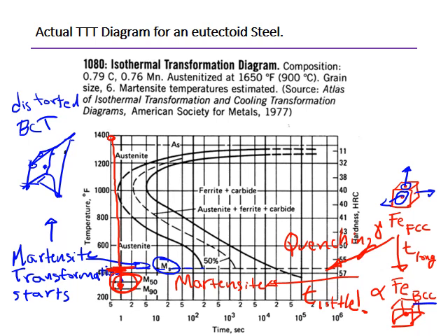The carbon atoms normally are somewhere there in the crystal, so the carbons didn't have time to travel to the proper positions, and the irons also didn't have time to travel. So you have a very, very distorted crystal, which is called Martensite, which, by the way, is very, very strong because of the residual stresses acting in the crystal structure, but fragile because lots of residual stresses are there. So it's very strong, but brittle.